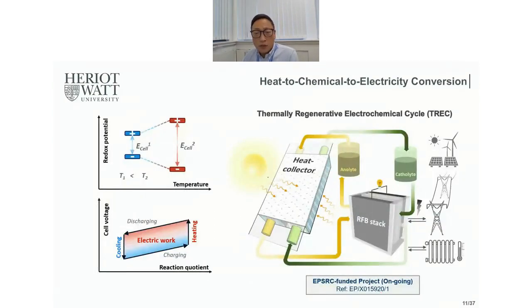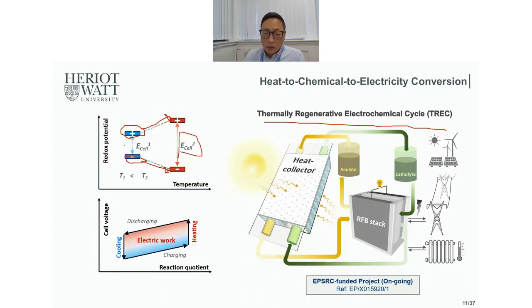Another type is the thermally regenerative electrochemical cycle, shortly called the TREC. The main driving force is the cell voltage shift at two different temperatures, depending on what redox couple you choose. Of course, this can be changed, but if one electrolyte has an increasing potential at high temperature, while the other one shows a decreasing redox potential, then the overall cell voltage increases. So by using this fundamental, if we charge at a low temperature, heat up, and discharge at the high temperature condition, then we can make electricity work between those two different charging and discharging curves, and this is heat harnessing here.